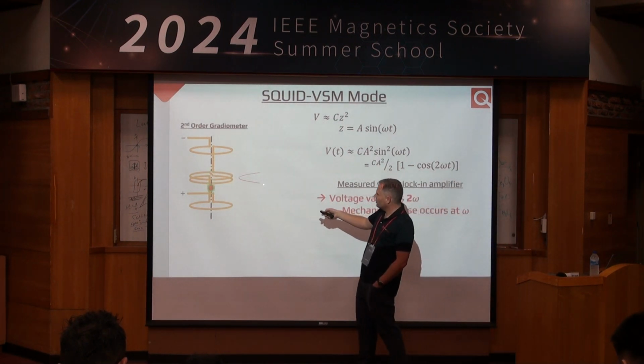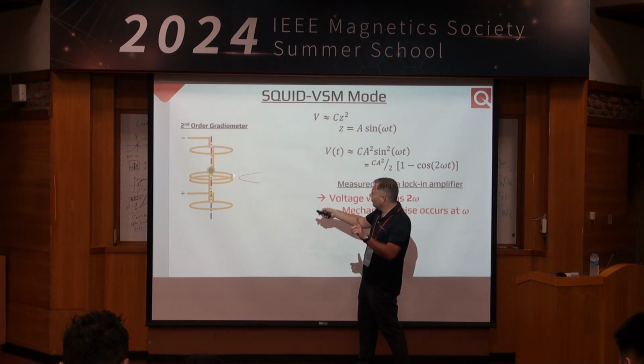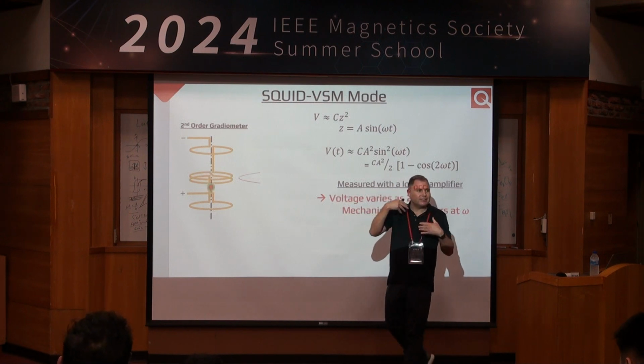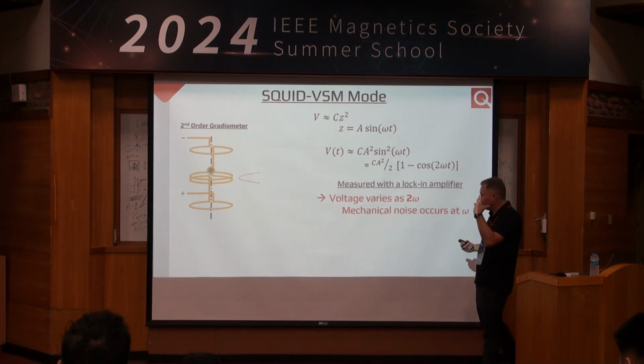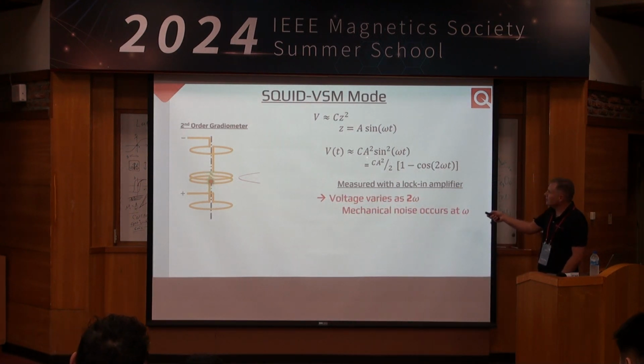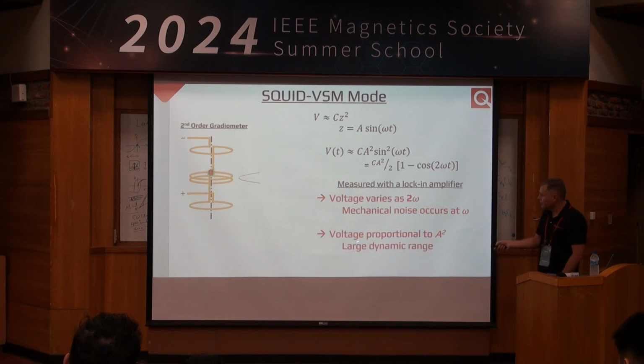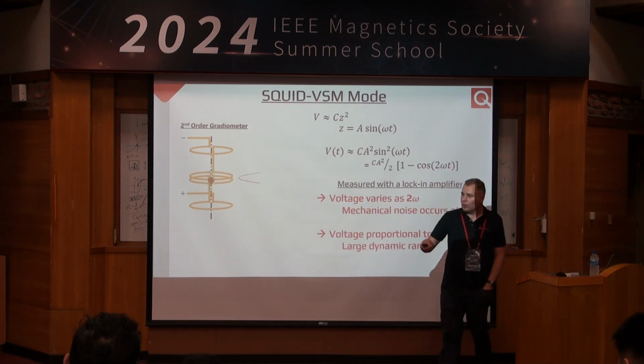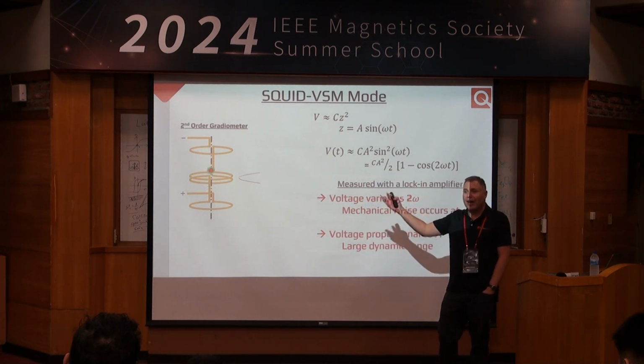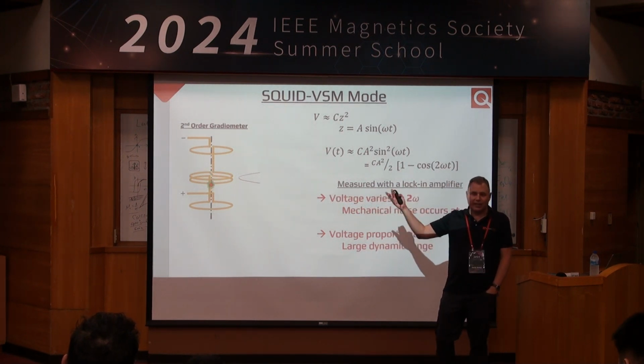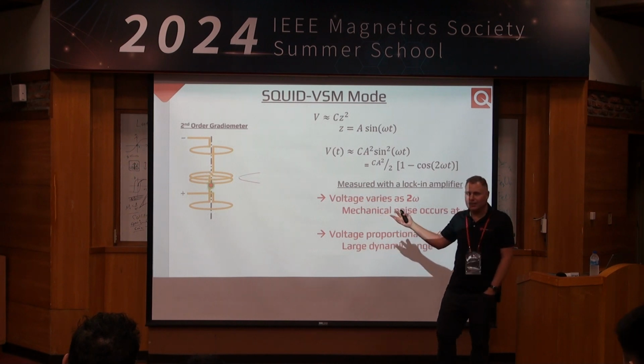So if you go through the little experiment here, let's say we move the sample through one physical period. Down, up, down. The voltage goes down, up, down, up, down. So you can see how it varies at twice the frequency. And we take advantage of that. The other interesting thing is that the voltage depends on the amplitude squared of the oscillation. That means we have an enormous dynamic range with the SQUID VSM mode. We can measure all the way from nano EMU levels all the way up to 100 or 1,000 EMU. So that's 10, 11 orders of magnitude in EMUs.